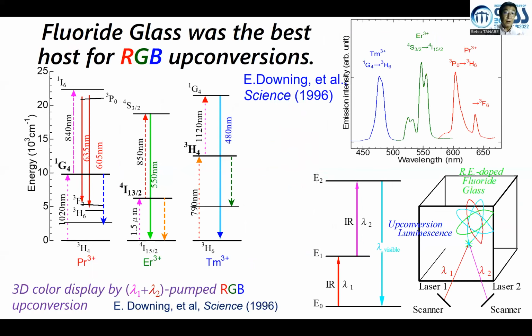And there are three luminescent centers: praseodymium for red, erbium for green, and thulium for blue. The important thing is we shouldn't pump by one wavelength, but we need to utilize two different infrared wavelengths in order to achieve a three-dimensional display. But anyway, this can be possible. Some students at Rutgers University were collaborating, supplying doped fluoride glasses.